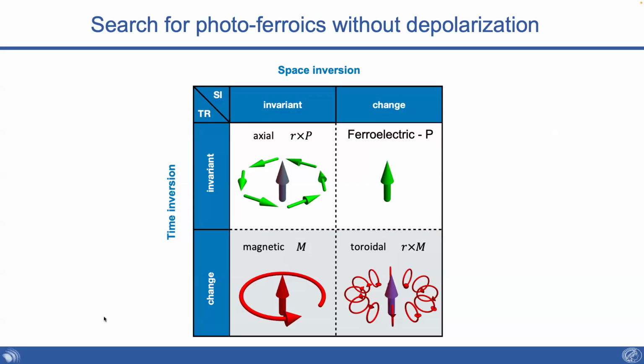A ferroaxial, you should think about this as a vortex of ferroelectric dipoles. So imagine you now have ferroelectric dipoles that wind around like so, or they wind around in the opposite direction. So this is a state that breaks neither inversion nor time reversal. And by extension, it will not have uncompensated charges. But by extension, I also will not be able to manipulate it because it doesn't couple to any field. So the conjugate field of this thing is some curl of E. It's an axial field, right?